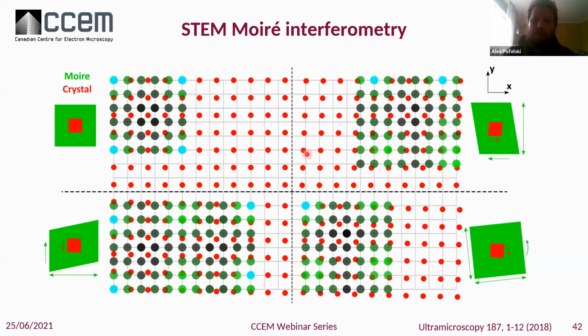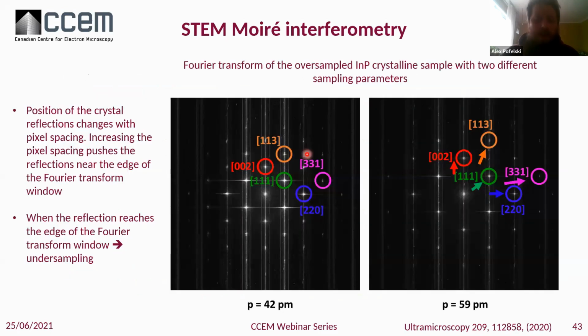We need a more detailed theory to take into account how the Moiré fringes change with strain. Again, we're going to look at that in Fourier space, because Fourier space gives you a very good, qualitative way of understanding what's going on. So this is a Fourier transform of the oversampled indium phosphide crystalline sample with two different sampling parameters. This is a condition of high resolution STEM imaging.